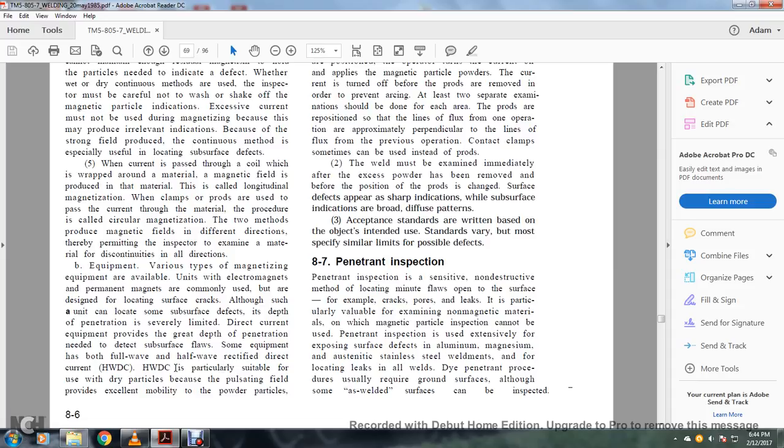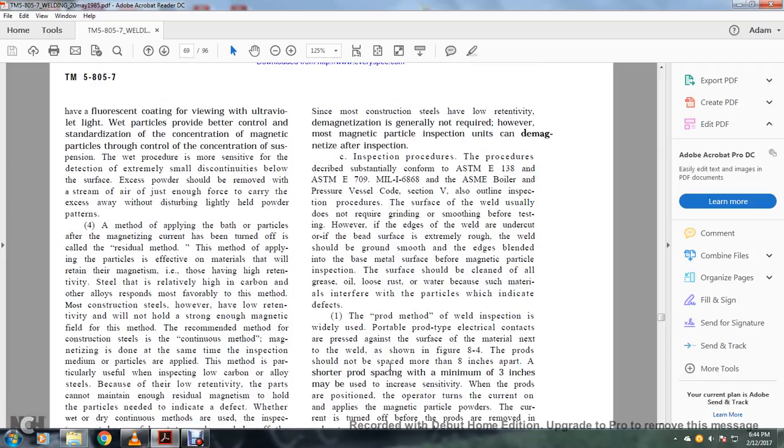HWDC, half wave rectified direct current, is particularly suitable for dry particles because of the pulsating field, which provides extra mobility to the powder particles. Most construction steels have low retentivity, so demagnetization is generally not required. However, most magnetic particle inspection units demagnetize after inspection.